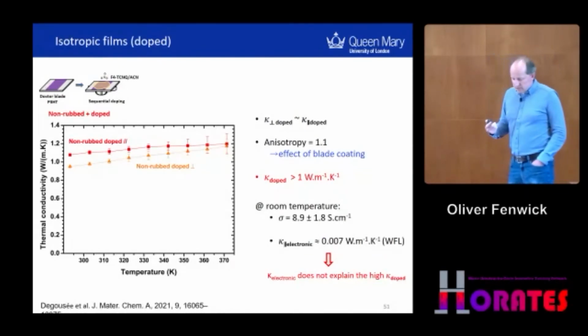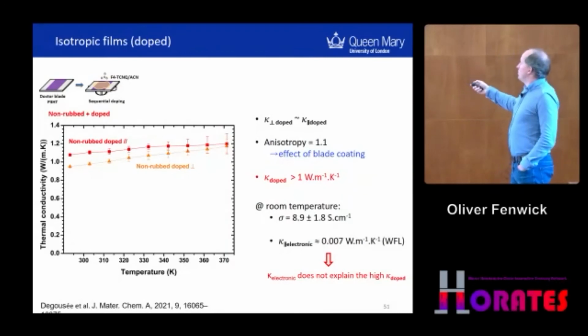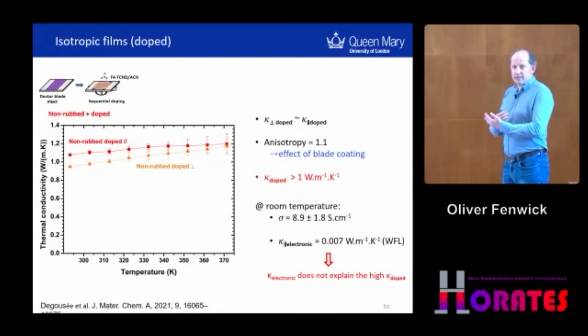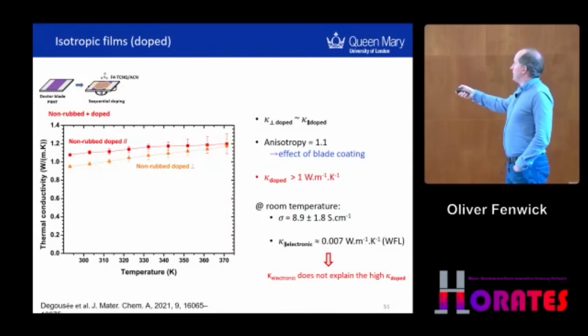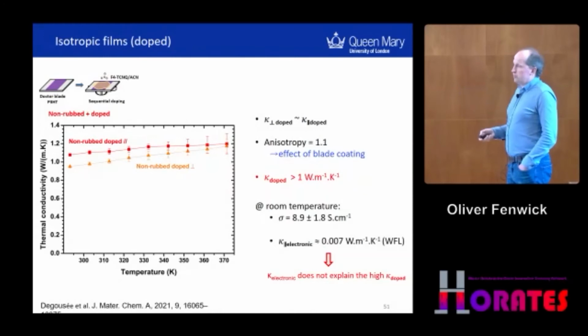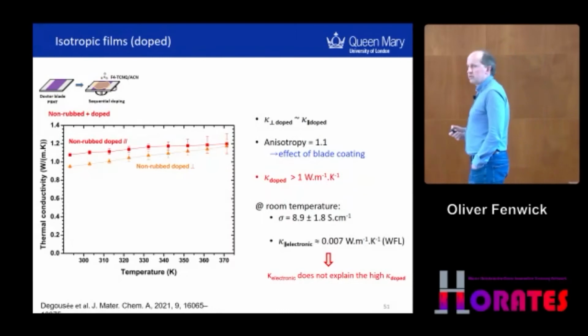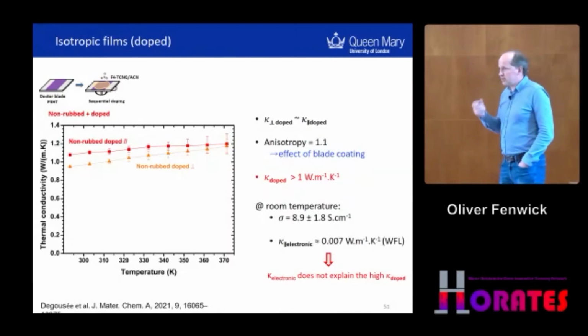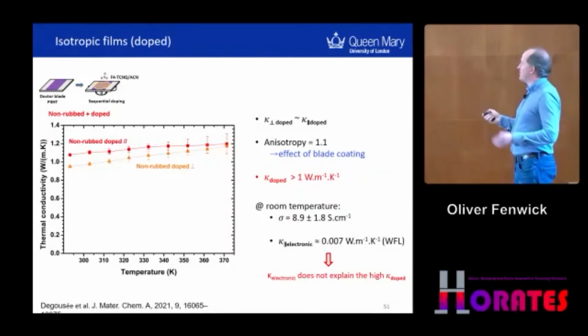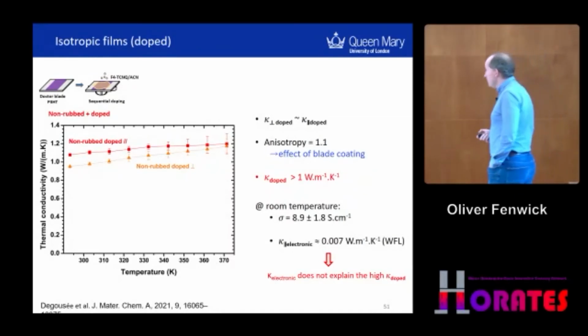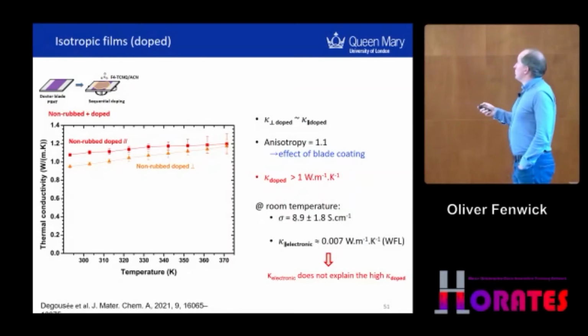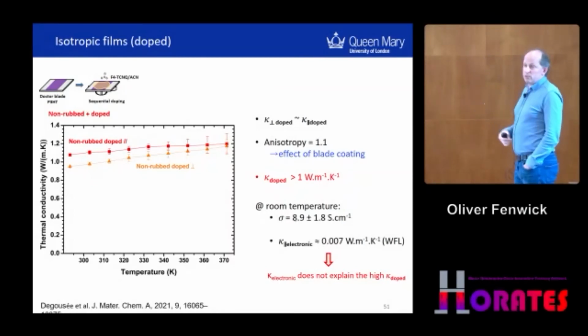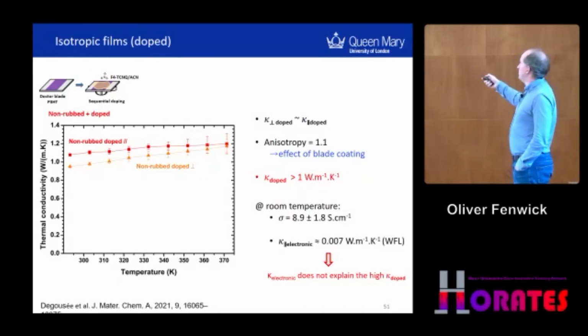The most surprising result for us was when we put in a doped sample that hadn't had the mechanical rubbing, and we were expecting something perhaps closer to the neat P3HT. It turns out that it came out around 1 watt per meter Kelvin, really rather large. And if the previous results didn't challenge the idea that polymers always have low thermal conductivity, this result, I think, should. There's a small anisotropy, which might be the effect of blade coating. There's a small anisotropy already in the films, but it is very minimal.